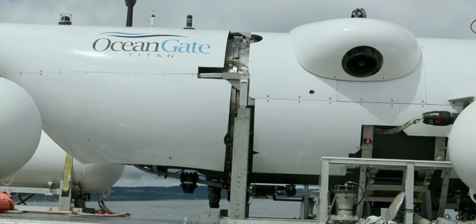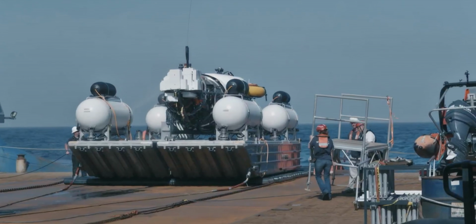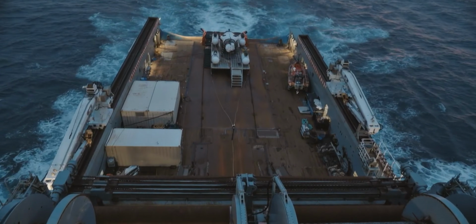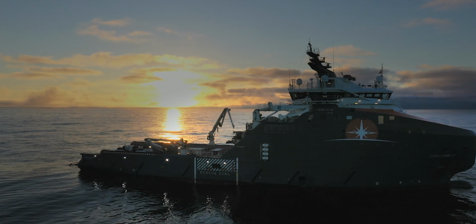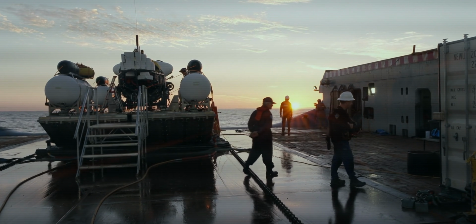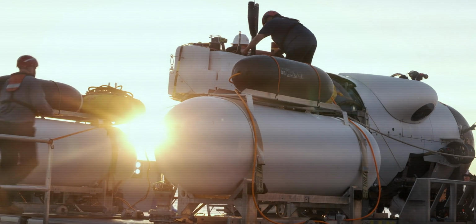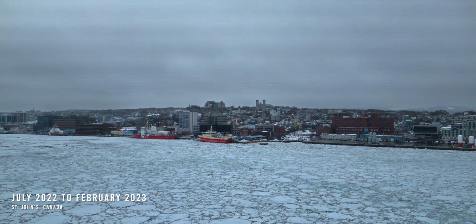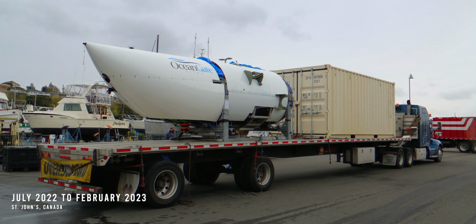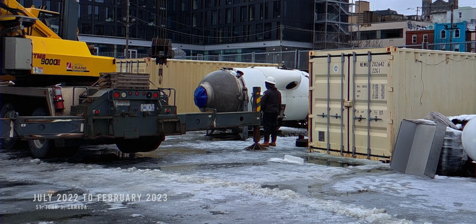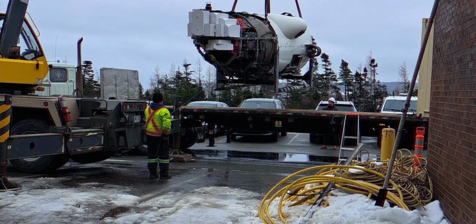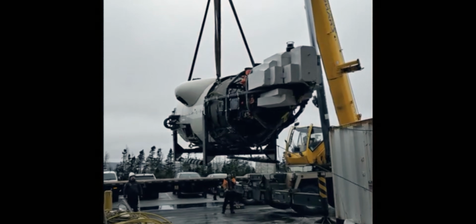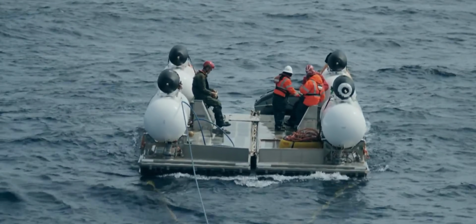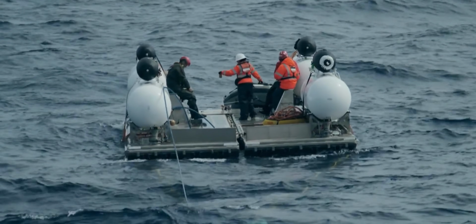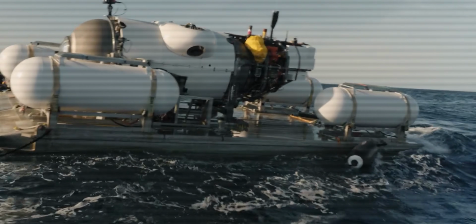Even after Dive 80, Titan continued operating under conditions that investigators believed may have worsened the existing damage. Composite pressure vessels are typically stored in climate-controlled environments to protect them from moisture, sunlight, and temperature extremes. Instead, Titan spent the winter of 2022 through 2023 uncovered outdoors in St. John's, Newfoundland. Investigators noted that if water entered existing delaminations, repeated freeze-thaw cycles could have forced the separated layers farther apart. The method of transportation also changed. Rather than being carried aboard its support vessel, Titan was towed approximately 900 miles across the North Atlantic behind Polar Prince. Already containing internal delamination, the pressure hull was subjected to continuous wave impacts, vibration, and bending loads throughout the voyage.